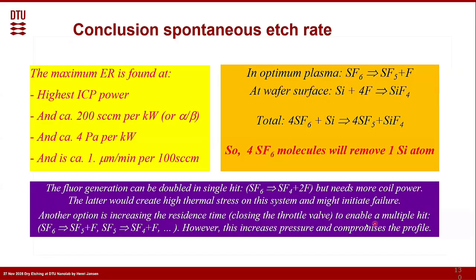Is that because the SF6 which is inside the reactor can create fluoradicals? But if the residence time, or the lifetime, of your SF6 input is long enough inside the reactor, for instance, if we would close the throttle valve completely and keep it like that, and we don't have any input anymore, then the SF6 is first of all, of course, cracked into SF5 and F. But the fluorine will be used for etching the silicon, and the SF5 is still there. So it will be cracked further to SF4. And also here, the equilibrium is shifted because the fluorine is eaten up by the silicon. SF4 will be cracked. So if you have a longer residence time, you can even go down to the very low levels where all the SF6 is used up.